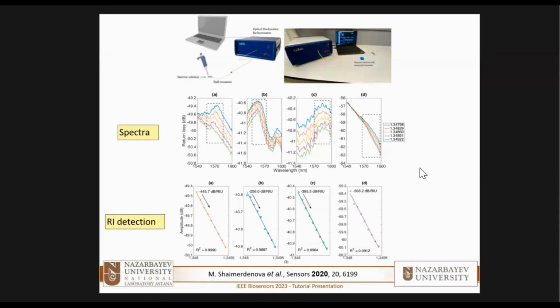The first thing that comes to mind is that although these are 4 very similar devices, the spectrum is totally different from device to device. And that's one of the common points of working in these approaches. The spectrum is almost random. So you have to deal with a random spectrum. But the sensitivity is quite large, and it goes usually up to several tens or up to a few hundreds of dB per refractive index unit when you track how the intensity changes in each point.